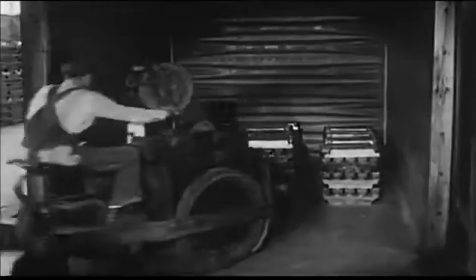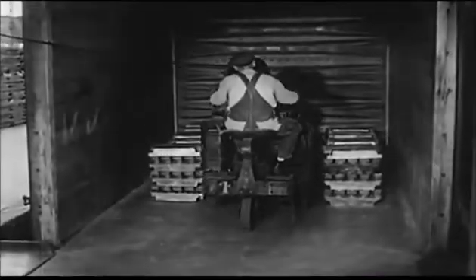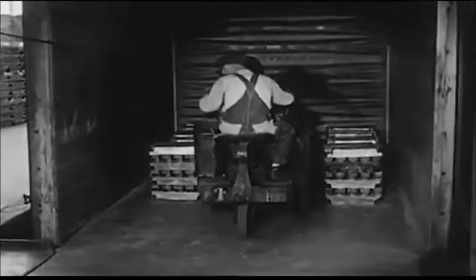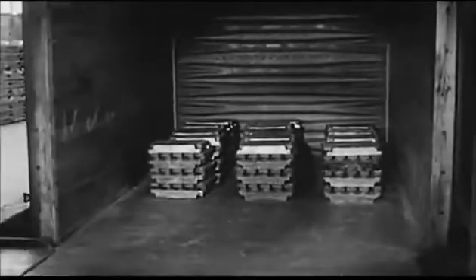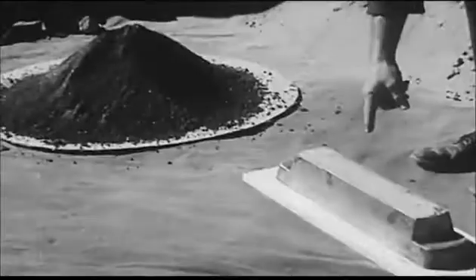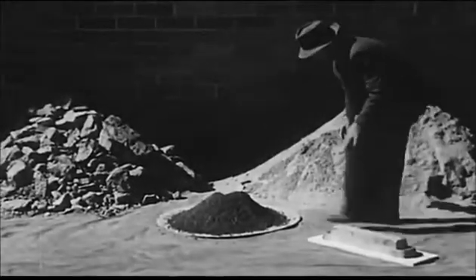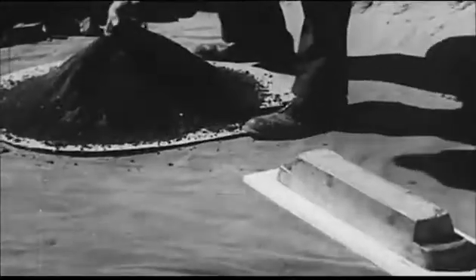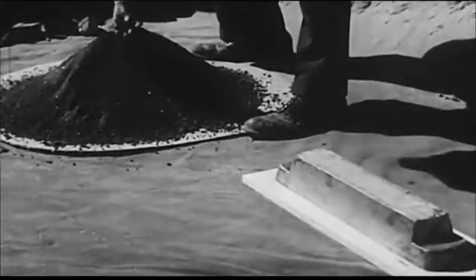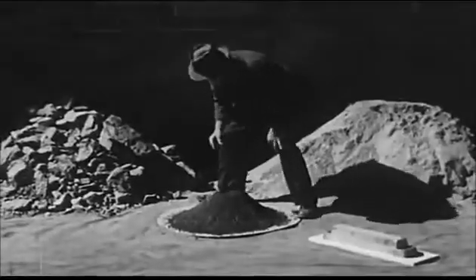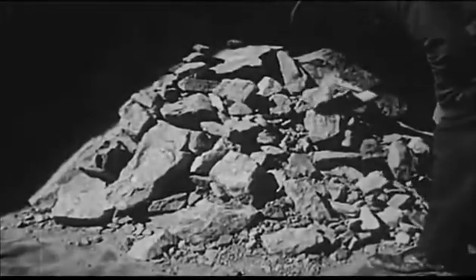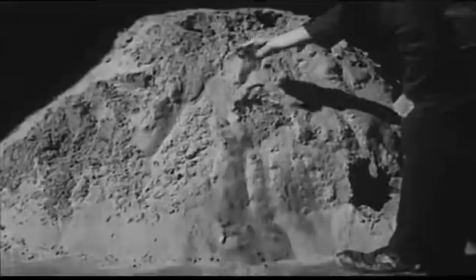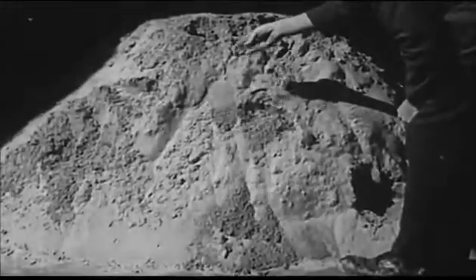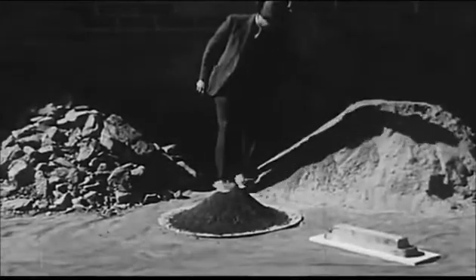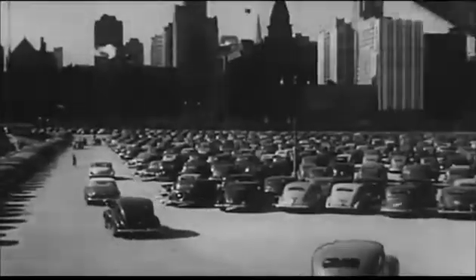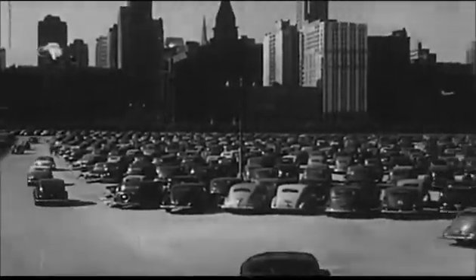With each car loaded to its capacity of about 50 tons, the metal lead is sent out to the many various industries to be converted into useful articles for mankind. This pig of lead, weighing 100 pounds, has been obtained from the smelting of about 138 pounds of concentrates, which by milling have been produced from approximately 3,300 pounds of ore taken from the mines. In the milling process, about 3,100 pounds of almost lead-free limestone was discarded as waste, locally called chat.